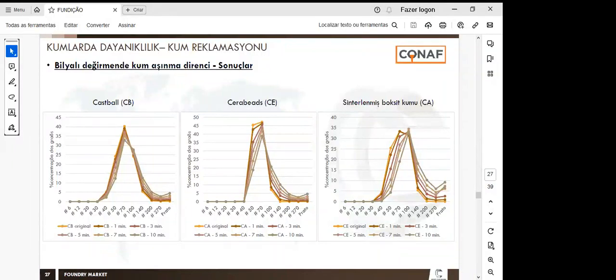Now we compare Castball with other types of ceramic sands, such as mullite and a bauxite sinterized alternative. And we conclude that ceramic sands present higher durability than natural sands, such as silica and chromite, but Castball presents the best results, okay? And the results are associated with the corundum phase that we saw at the beginning. Castball's main phase is corundum.